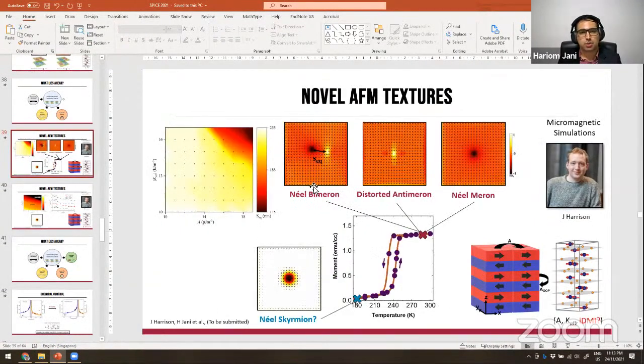I think this one here. So, for example, the intermeron core, written here as SQ, actually can be mapped and evolved as a function of the exchange as well as the anisotropy, and we can actually have a very rich phase diagram where they are effectively very far away from each other, that they behave almost as independent entities, and then in the upper right corner here they come very close to each other, and therefore they behave almost as if they are coupled to each other. And we ideally want to be in the smaller regime so that we can control them for textures for any kind of systematic use.